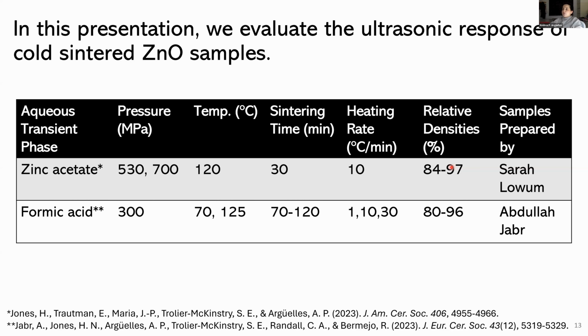So what we did is we took 2 sets of cold sintered zinc oxide samples, and the main difference here was that we dealt with 2 different transient phases. That liquid phase that I talked about that facilitates sintering, I'm going to come back to that, because it turns out that the transient phase is critically important, and ultrasound allowed us to identify some of the ways in which it affects the final part. So we did 2 sets of that, and you see that we have a range in the relative densities that goes from 80 to